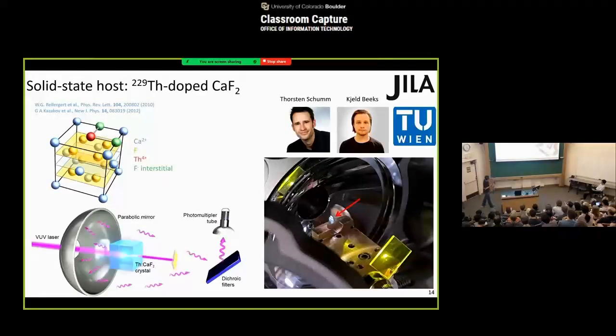So essentially what we do in the experiment is we shine a VUV laser onto this thorium-doped crystal for about 400 seconds. Then we turn off our VUV laser and collect the fluorescence photons emitted by the thorium nuclear transition inside this crystal using a parabolic mirror. These photons are sent through a set of dichroic filters and eventually to a photomultiplier tube where we can count individual fluorescence photons. If we were able to successfully excite the thorium nuclear transition, we will see a higher photon count rate on our photomultiplier tube.